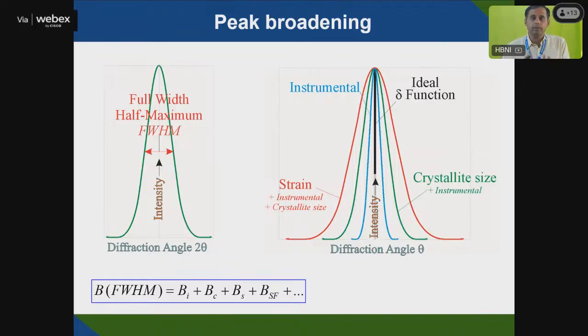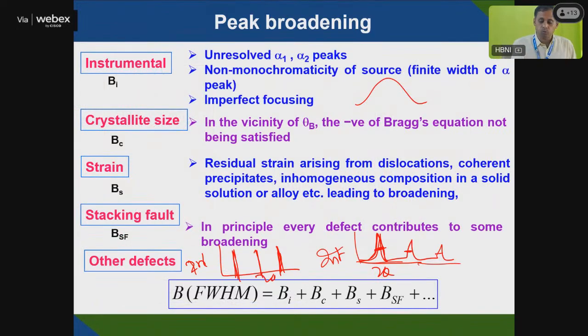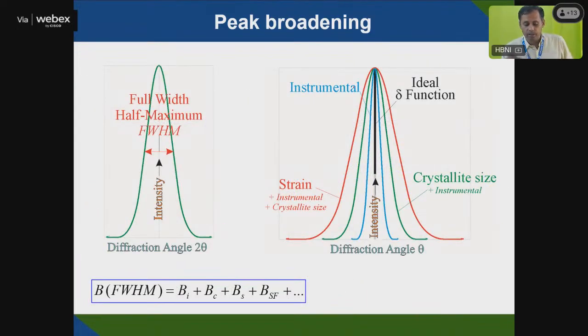This broad pattern is a mixture of many things. The broadening is due, first, to instrumental broadening: alpha 1 and alpha 2 peaks, the monochromaticity of your X-ray source, and whether it is properly focused or not give you instrumental broadening, BI. Then there is crystallite size: when you go smaller and smaller, your peak gets broadened, giving BC. Then, in going to nanoparticles, you build up strain in the lattice, which gives the strain factor. And if there are defects like stacking faults, they also contribute. So the total peak broadening is the summation of instrumental broadening, strain, crystallite size and defects.